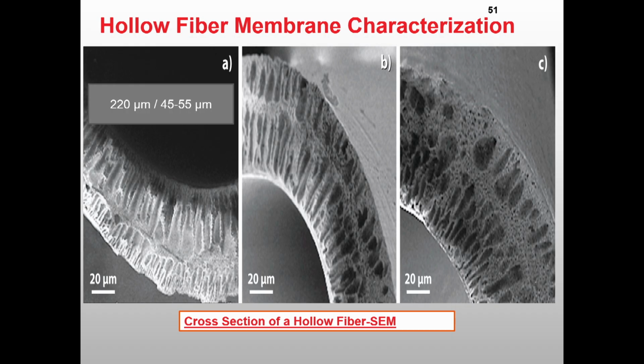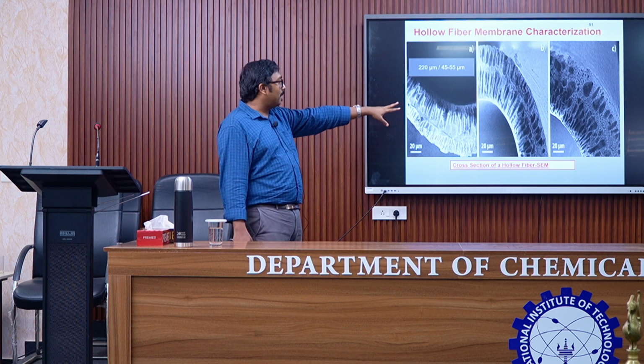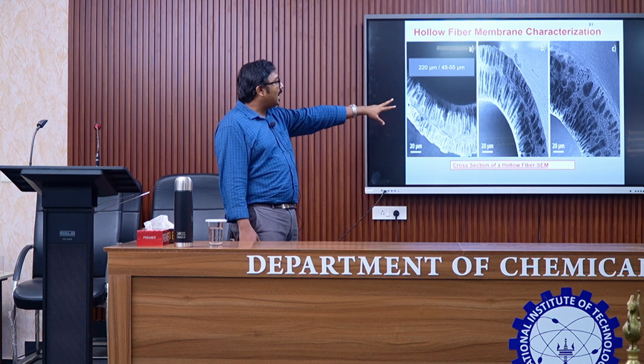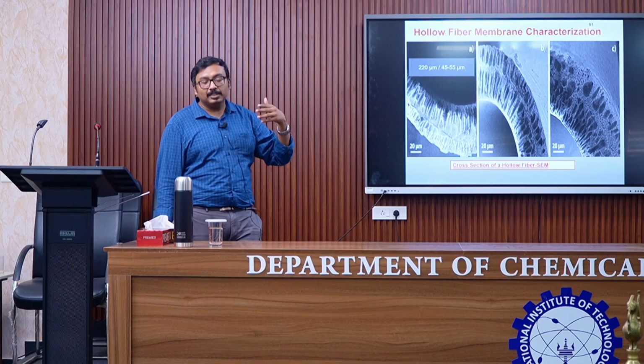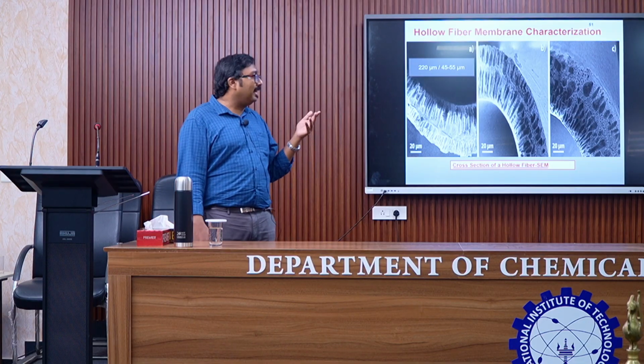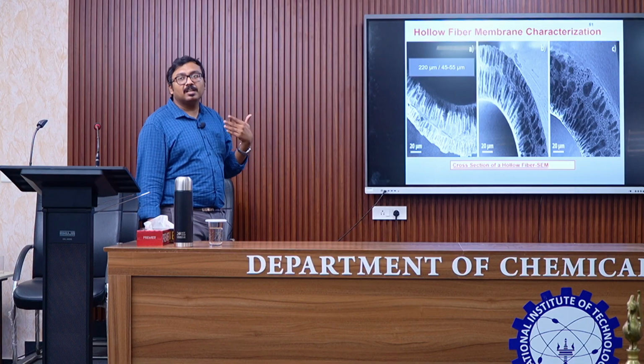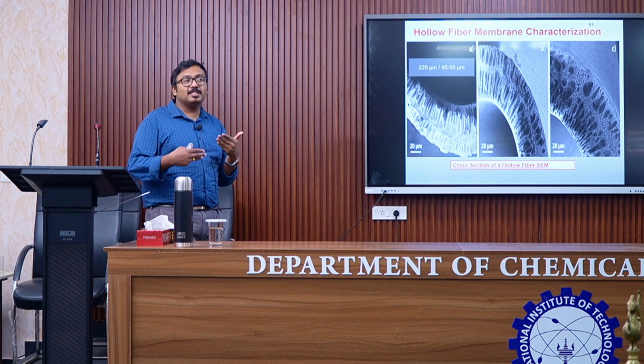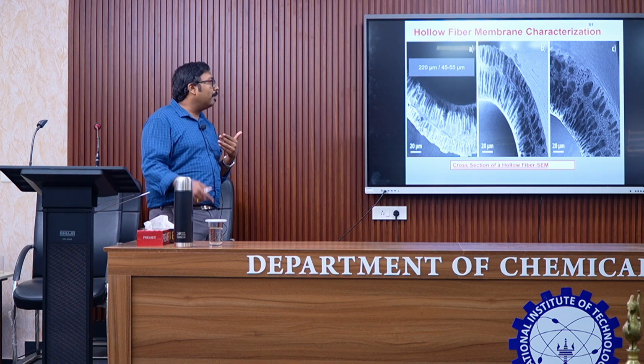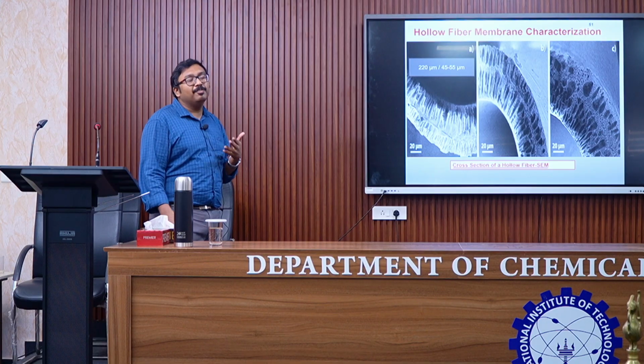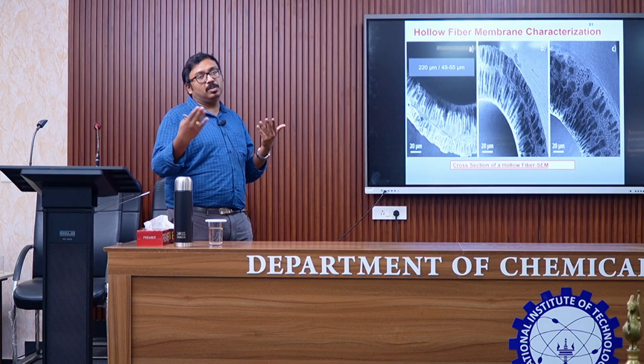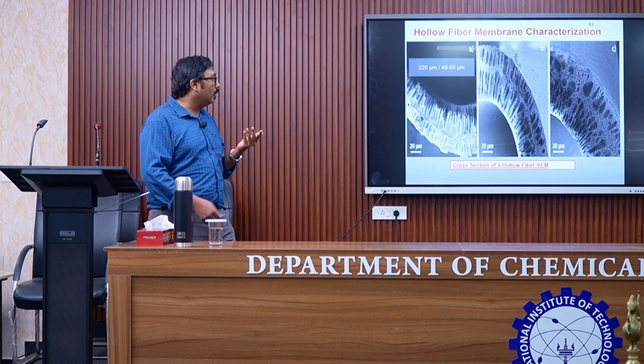You can see how the membrane morphology, or the cross-sectional morphology, changes when we add carbon nanotubes. Here you have more porous membranes as compared to here, and larger pores. When you have larger pores, it in effect leads to faster ultrafiltration fluxes, so your water permeation flux through your membrane automatically increases. But if the pores are very large, then all the solutes or the blood itself crosses over, which we don't want.